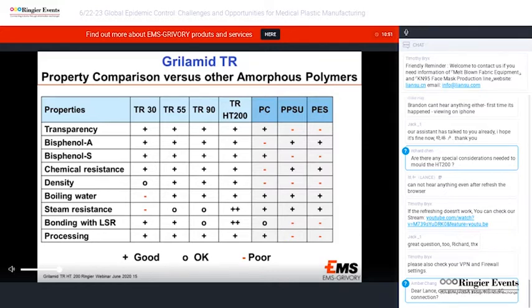For bonding to LSR, or silicone, a growing requirement in medical and other applications, Grilamid TR shows a good ability, with the TR HT 200 showing the best ability due to its high glass transition temperature and corresponding higher heat deflection temperature, allowing higher curing temperatures of the silicone, considerably improving production cycle times. Sulfones, on the other hand, generally have poor adhesion to silicones. In regards to processing, the Grilamid TRs show a clear advantage over the sulfones due to the higher processing temperatures required for sulfones.